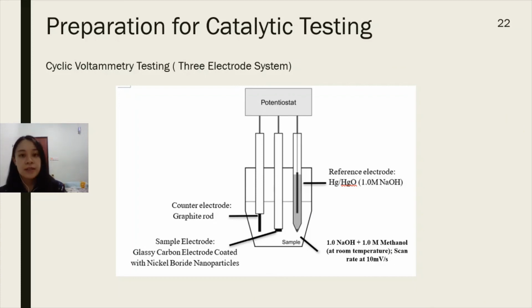So for the catalytic testing, we'll be using cyclic voltammetry testing or the 3-electrode system where all three electrodes will be connected to a potentiostat, and the counter electrode will be the graphite electrode. The sample electrode will be glassy carbon electrode coated with nickel boride nanoparticles, and then the reference electrode will be the mercury oxide electrode. While for the electrolyte, it will contain sodium hydroxide and also methanol.